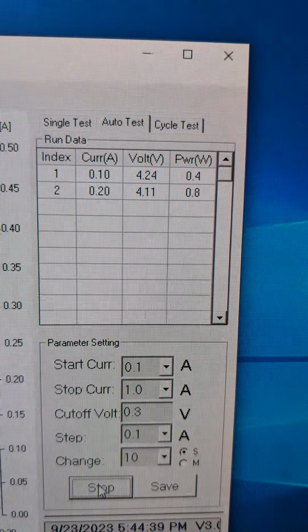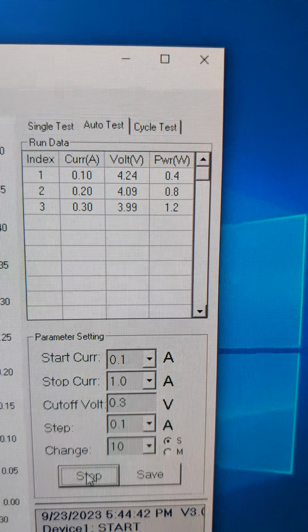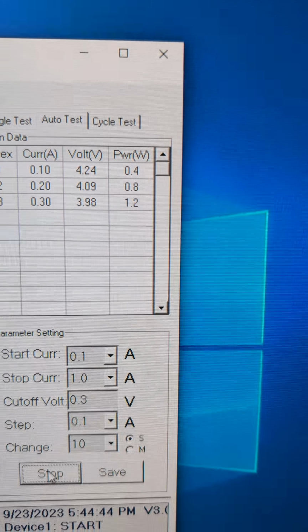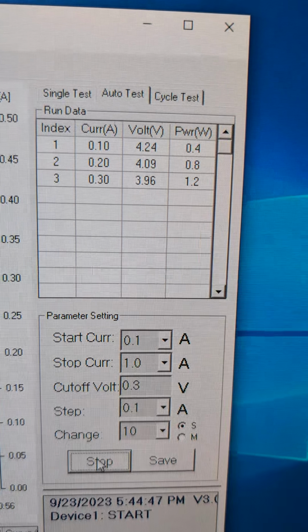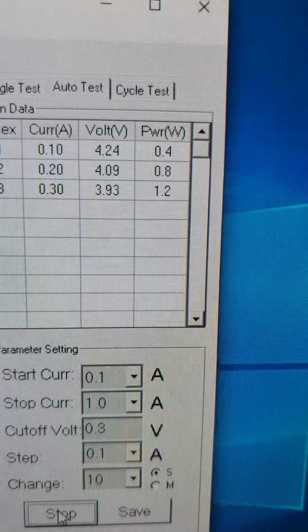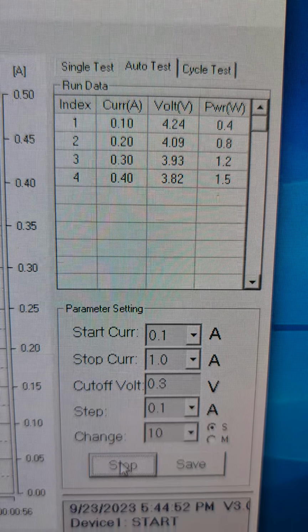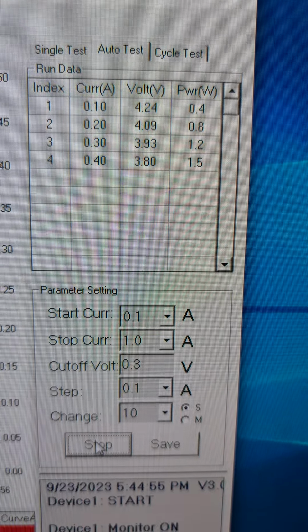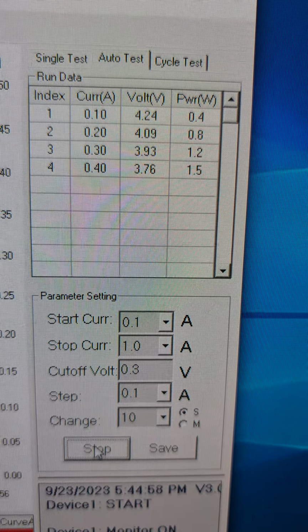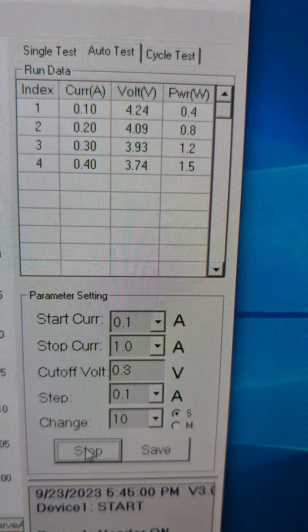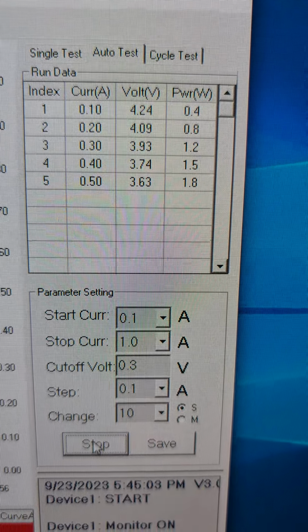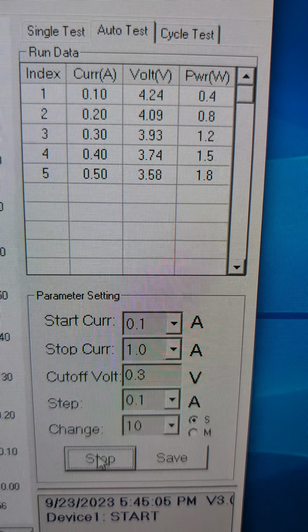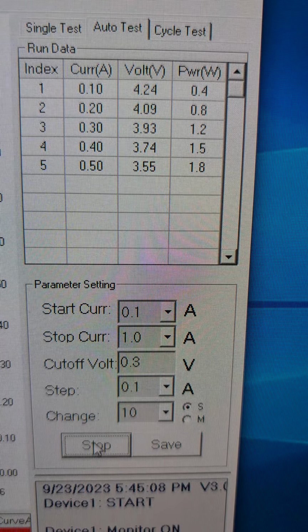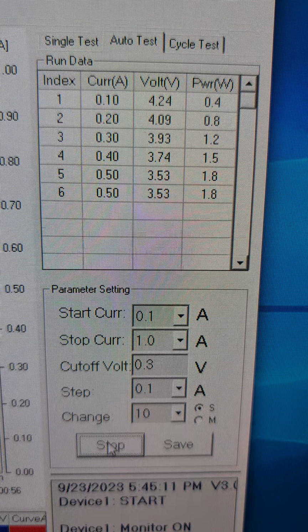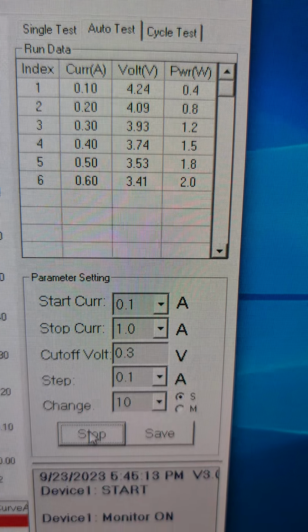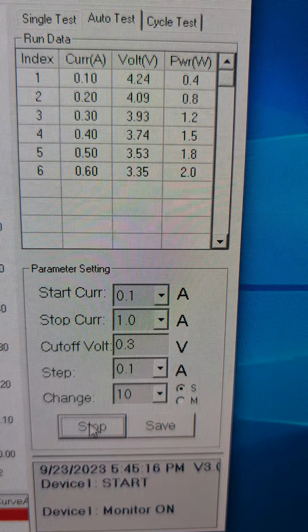Here's the first step with a feeble 100 milliamps. There's the voltage, and there's your power in watts, 0.4. Then we're up to 0.8, 1.2 for the third step. Going up, power output as the current's going up. So at 400 milliamps, step 4, you can see 1.5 watt output, 1.8. Let's see if we get a 2. More about that in a second. There it is.